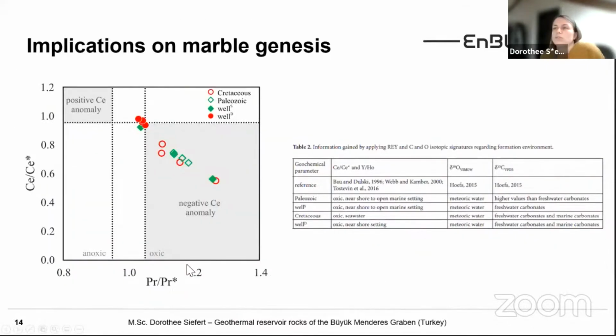Also here maybe just shortly about the rare earth elements. We could show we had different cerium anomalies, negative cerium anomalies, which point to a seawater origin, and also the positive yttrium anomalies indicating a seawater influence. And as the Cretaceous and Paleozoic limestone protoliths formed on the shelf of the Neotethys, they must be marine.